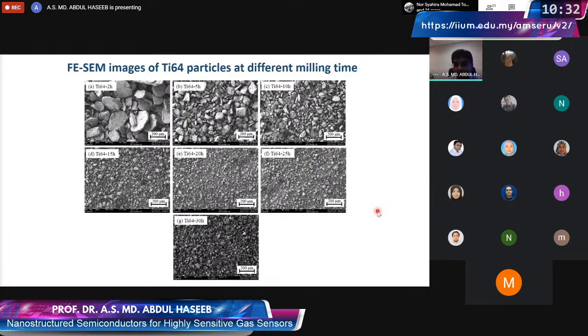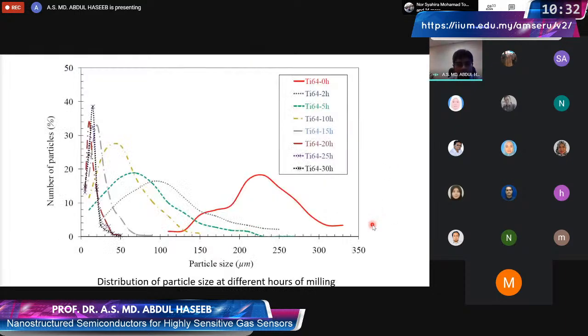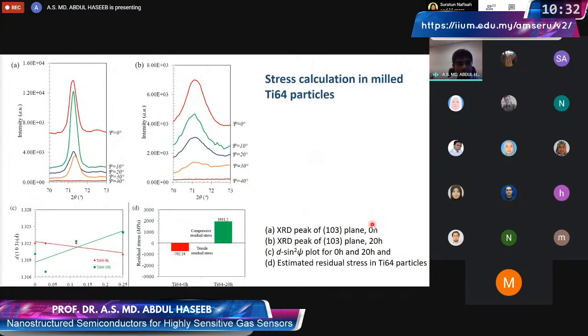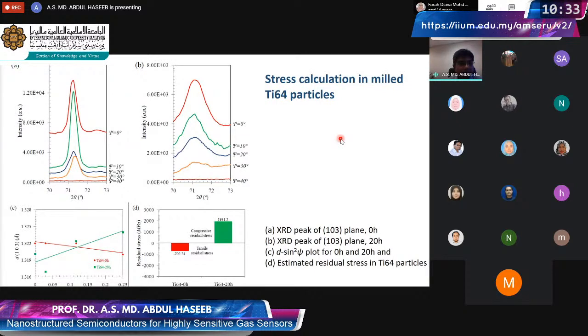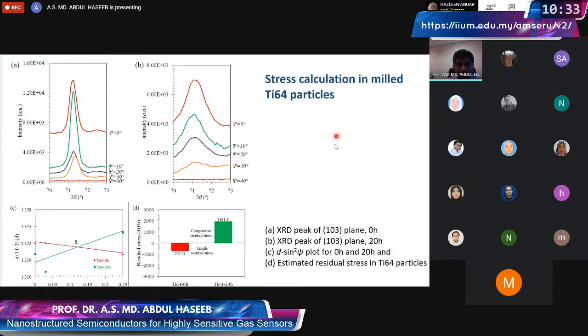I think I skipped the particle size distribution. What I want to show is this one. As a result of ball milling, we induce stress, as we all know, and we wanted to calculate the residual stress inside. We use this d sine square chi method from X-ray diffraction, and we analyzed the intensity of the 103 plane of this titanium particle. And what we see here is this.